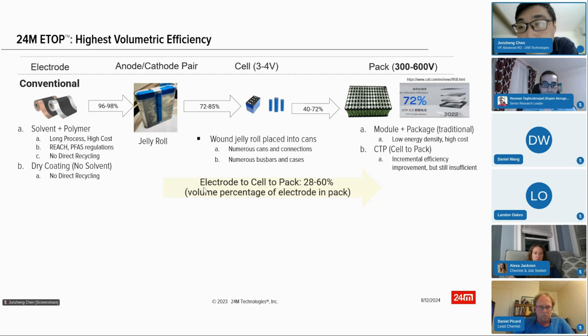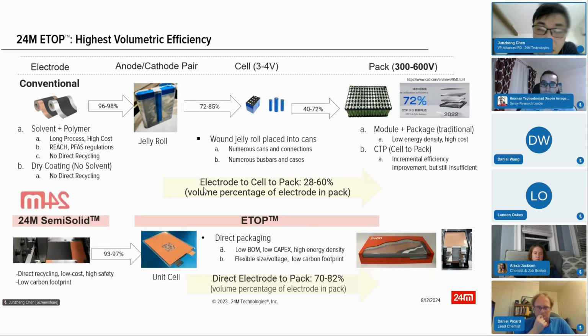But that was the cell to the pack efficiency. You still need more than 500 to 800 cans in this pack. Those cans will become your burden and reduce your energy density quite a bit. Our concept is because we have SemiSolid at the beginning, and well electrolyte confinement within this unit cell bag structure, then we use this bag structure to put it directly into a pack.